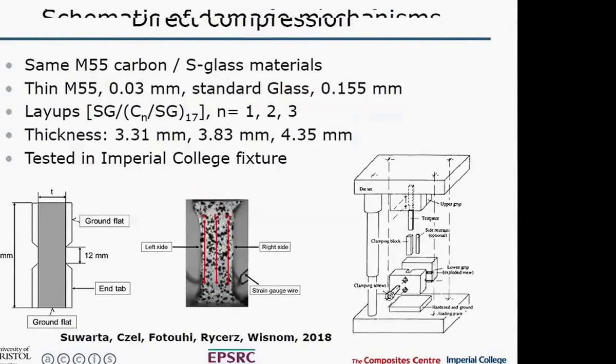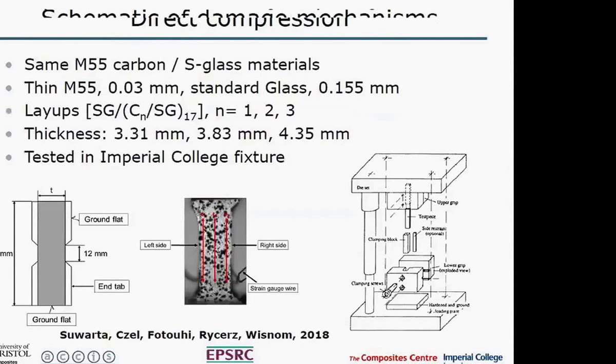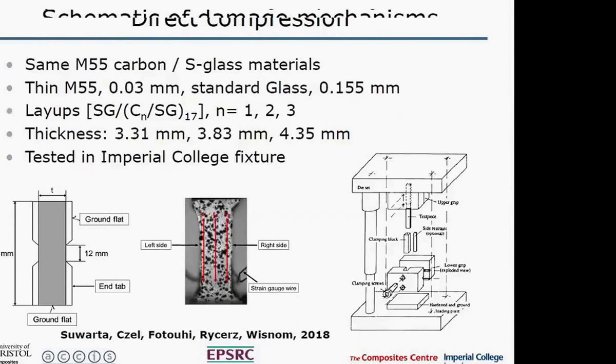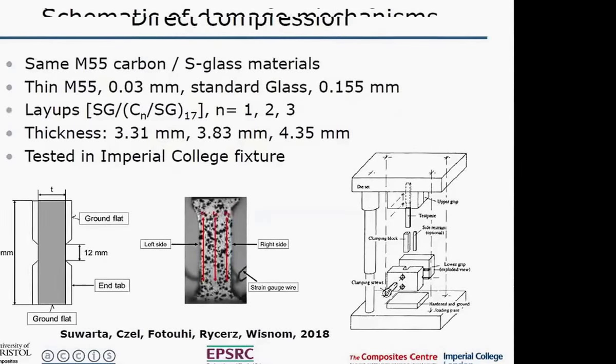Then we went on to look at what's happening in direct compression. We've done some tests on the same thin M55 and standard S-glass materials we had before, loaded in direct compression in this Imperial College rig. The layout now is S-glass, carbon, S-glass, but this time we've changed the number of carbon plies. We've done 1, 2, or 3 carbon plies together in this block, which is repeated 17 times. In this hybrid, we're varying both the proportion of carbon to glass and the thickness of the individual carbon plies, and seeing how that affects the compression behavior.